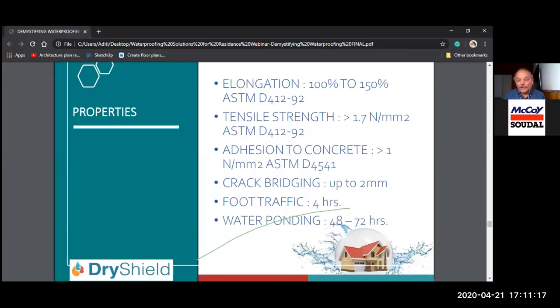Now, when I talk about water ponding, what happens at most construction sites is that a waterproofer will say, sir, I will do the work today, fill water and test tomorrow. Nowhere does a manufacturer specify in the data sheet after how many days it should be ponded with water for testing. Yes, a few companies do, but not everyone. Ideally, it should be a minimum of 48 hours in summers and 72 hours in winters. Before that, if you pond it with water, there will be problems. I have seen a film formed on top of the coating, which should not form if the coating has cured. A minimum of 48 to 72 hours is required for curing of the coating.